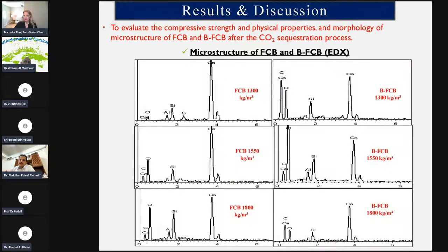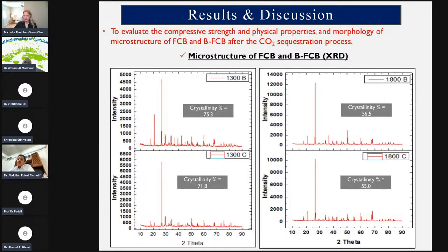On the other hand, by using EDX, we can see the calcium in the biofoam concrete compared to foam concrete has decreased. Why has the calcium decreased? Because the bacteria used the calcium located in the cement to precipitate calcium carbonate. So in the EDX result, calcium is reduced in the matrix using biofoam concrete, because some of the calcium in the concrete was used in producing calcium carbonate, which has the main role in the self-healing of the porosity.